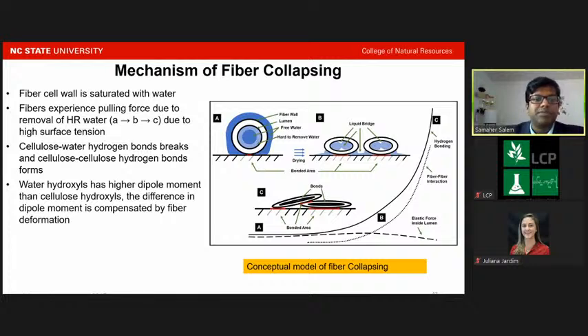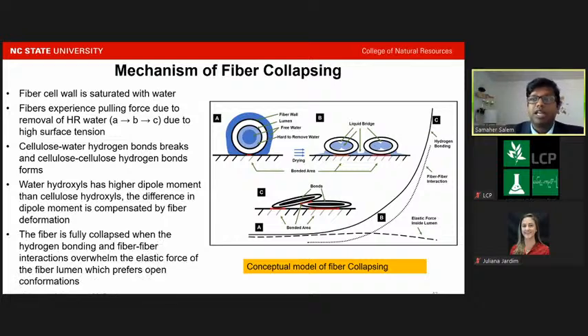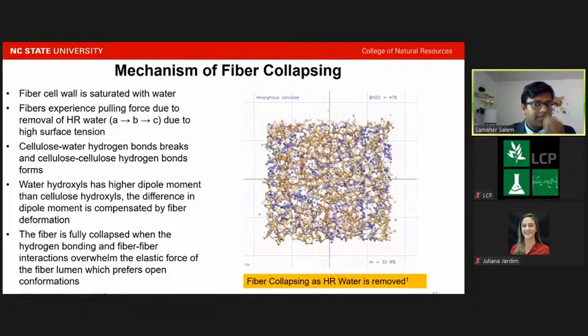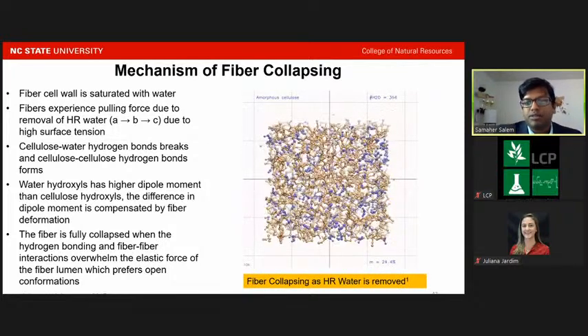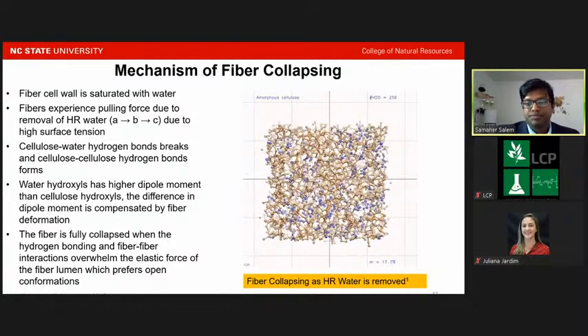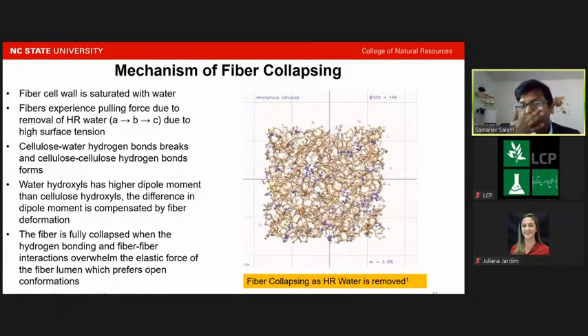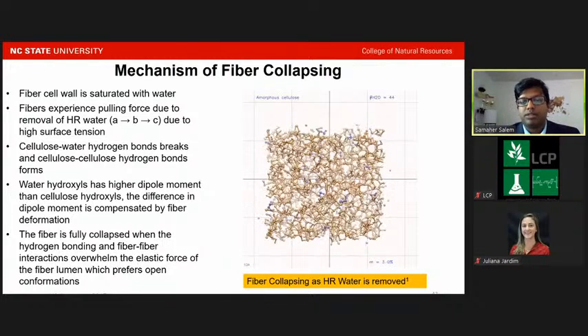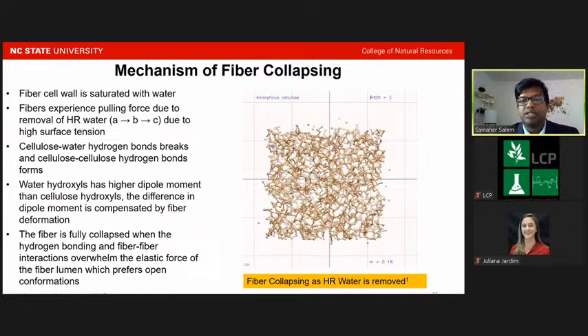The water hydroxyl has higher dipole moment than cellulose hydroxyl. The difference in dipole moment is compensated by fiber deformation, and the fiber is fully collapsed when the hydrogen bonding and the fiber-fiber interaction overwhelm the elastic force of the fiber lumen, which prefers the opening conformation. And this is the simulation which shows how, when we try to remove the water, the fibers come close to each other and suffer collapsing, which is known as fiber hornification as well.